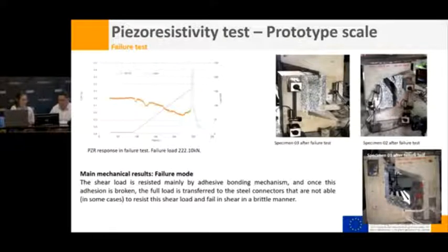These three images correspond to the three failure tests performed, the push-out tests. All of them failed in shear mode. But in some of them, the connectors maintain the bond, while in others, as you can see here, they were not able to resist the failure. Here, the shear load is resisted mainly by the adhesive bonding. And once the adhesion of the mortar is broken, the full load is transferred to the connectors, and they could fail or not.